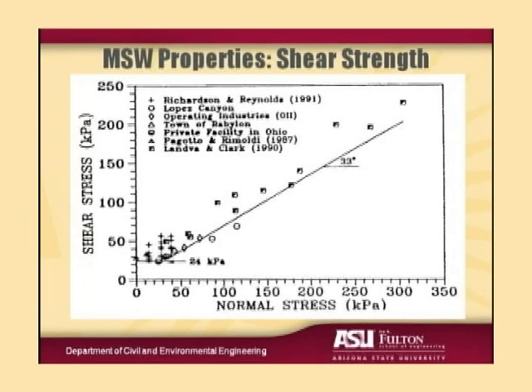So we went out and collected all of what we considered to be reliable information on large-scale testing of solid waste, and then did back analyses of stable slopes at 4 landfills with very steep slopes, including the OII landfill. So the little diamonds you see at about 50 kPa and 75 kPa, right on that 33-degree line, represent back analysis of the OII landfill. You'll notice 2 points below that line, 2 circles. That's the Lopez Canyon landfill, north of Los Angeles. We back calculated these shear strengths using a static factor of safety of 1.1, since these were stable slopes.